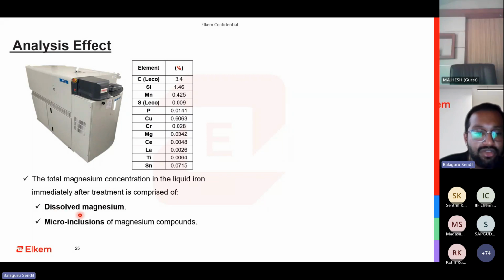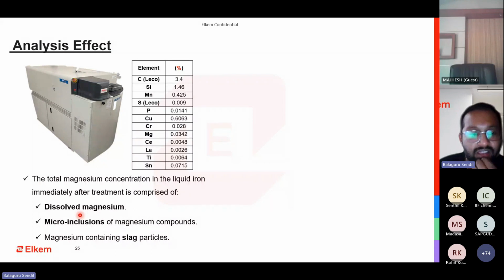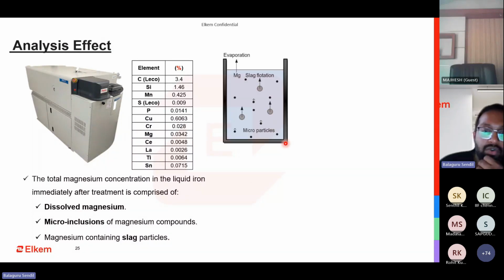And the other is the magnesium inclusions, that is the MgS and MgO. Inclusion means these are non-metallic compounds, magnesium inclusions. And the third one is the magnesium-containing slag particles. If you look at it pictorially, you have the magnesium here, which has created microparticles, which are quite stable, 1 micron in size, the MgS particles.